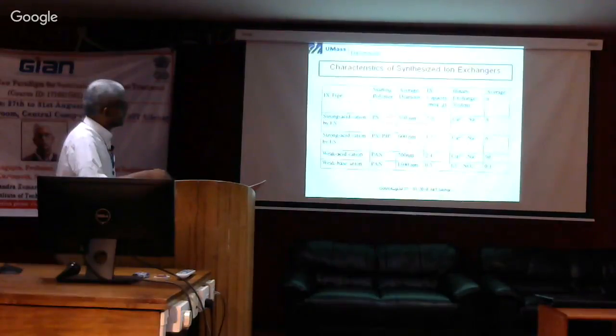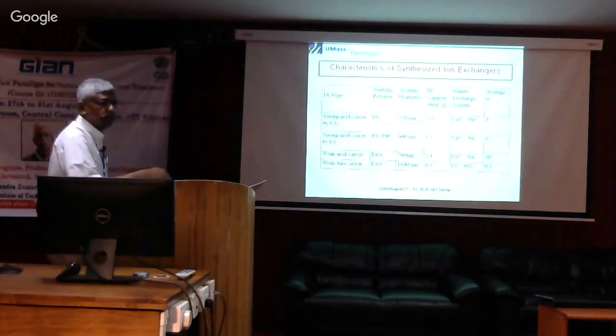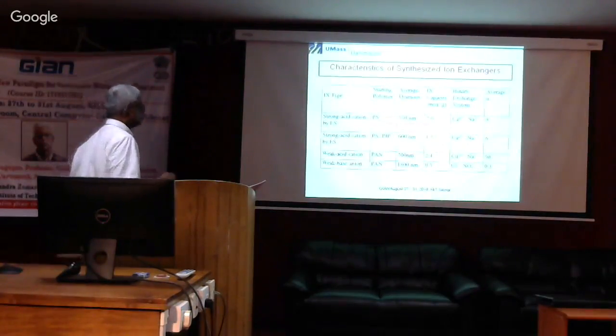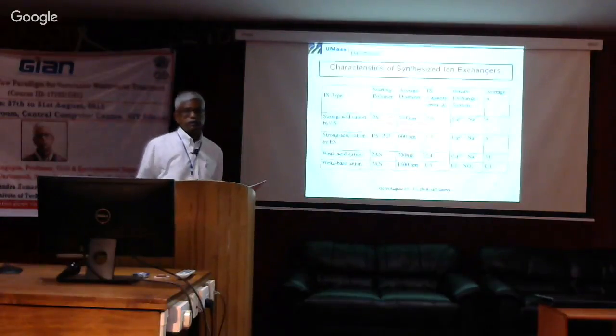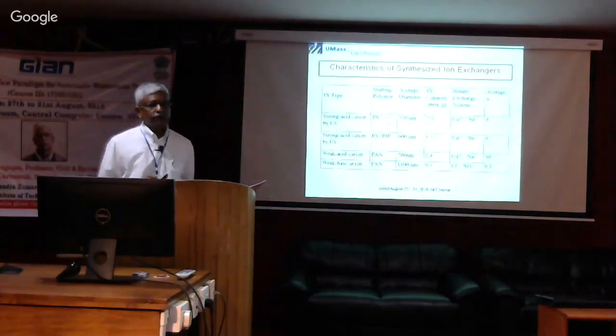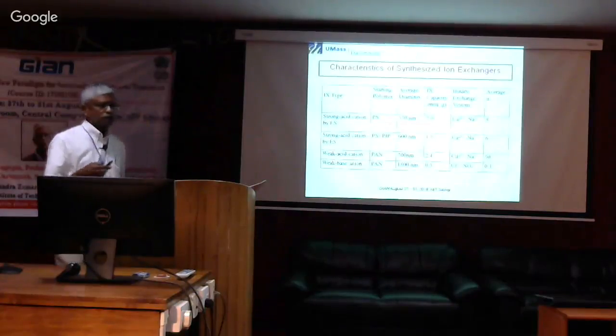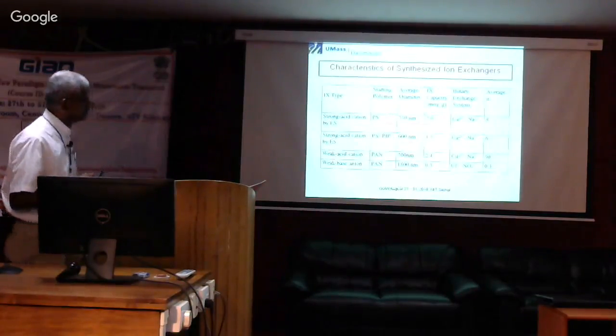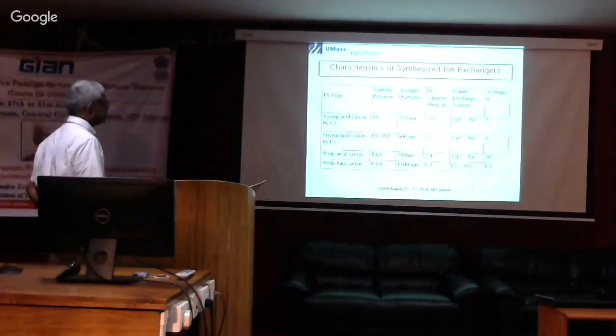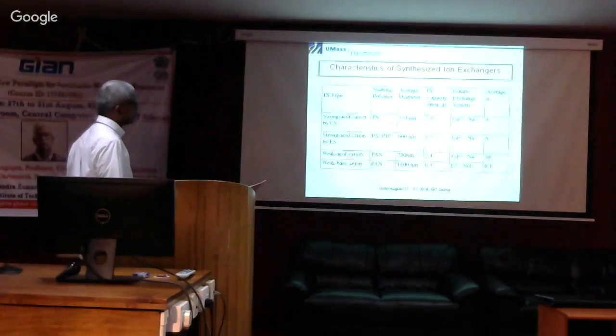If I take, again, a polystyrene, but now mix it with polyisoprene, if you look at the literature, a lot of people do that because that provides you with much more mechanical stability, physical stability. So when you do that, you get pretty much the same average diameter, a little reduced capacity, and a little reduced separation factor.